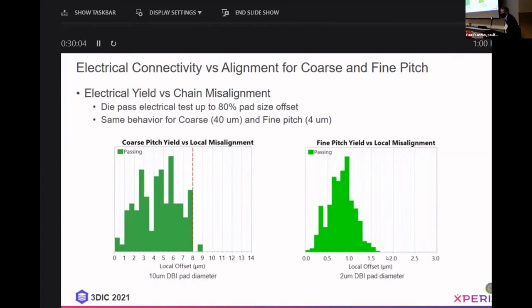Well, we did see some effects on the alignment that looked like they were due to our bonding tool. We saw some localized misalignment that was the same from wafer to wafer on our bonding tool, and on our partner's bonding tool they didn't see that same misalignment. So there could be some tool related alignment issues in this data. I guess the main point of the data was that the electrical connection was good out to 80% pad size offset.